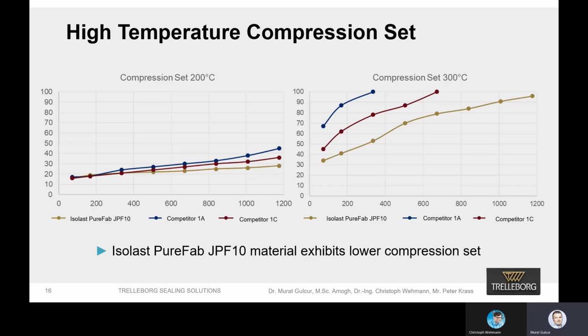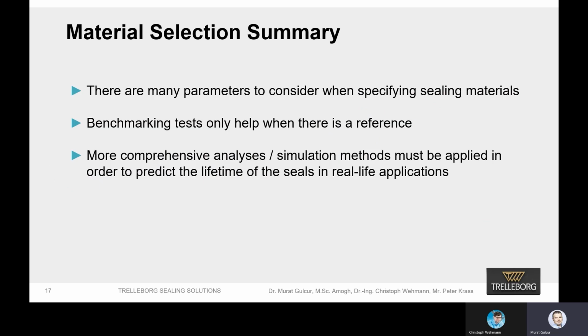On this compression set chart, you can see 3 materials are tested. One of them is our JPF10 material against 2 different competitor materials, and we did this test for quite an extensive time, more than 1100 hours at 200 degrees on the left-hand side and 300 degrees on the right-hand side. We found out that the technology we developed has significantly better compression set, a lot lower compression set than the competitor materials, even at high temperatures.